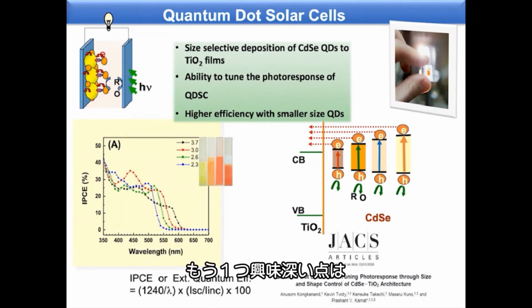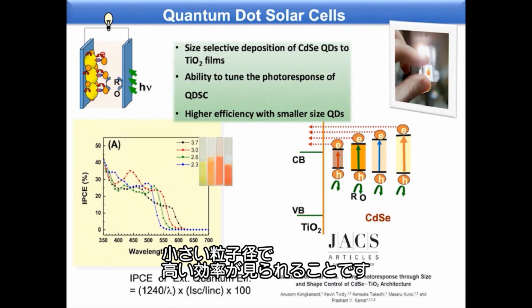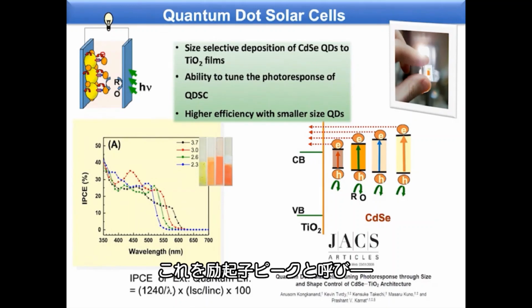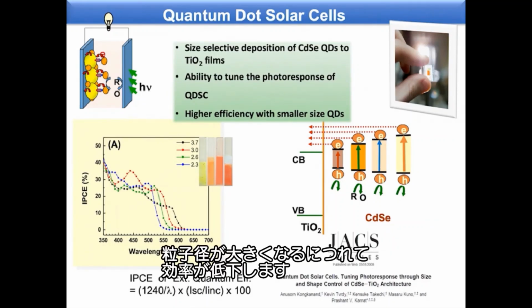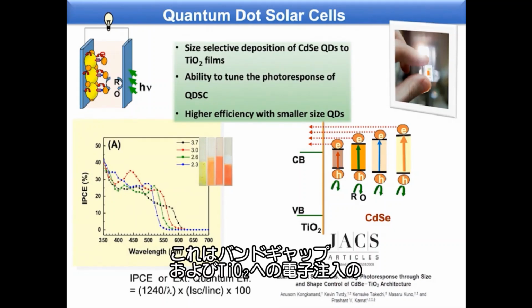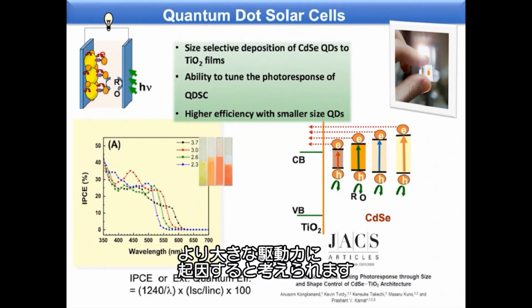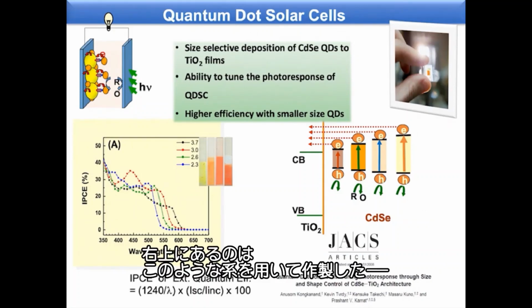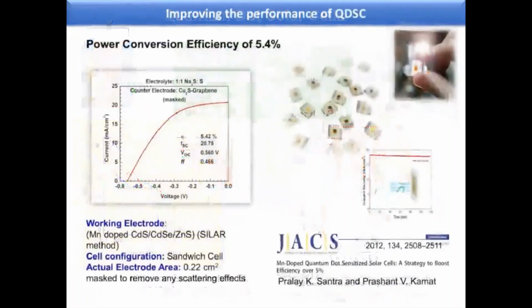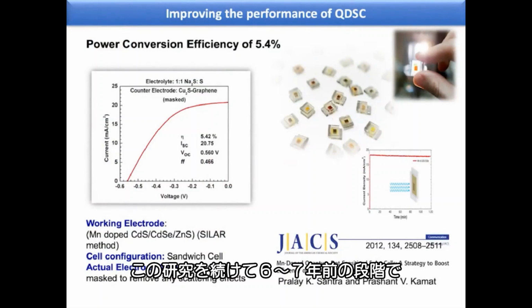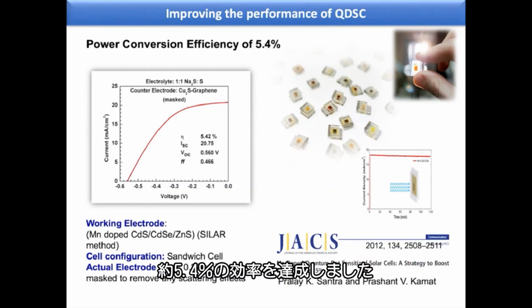Another interesting aspect was the higher efficiency that we see with the small size particle, what you call the excitonic peak, and it decreased as we increase the size, and that we attribute to the band gap and more driving force for getting the electron into the TiO2. So again, on the top right corner is shown what they call a sandwich cell we make with these kinds of systems. We continued our studies, and at that time, this is 6-7 years back, we got about 5.4% efficiency, and it shows you how we can get a very stable performance in these systems.